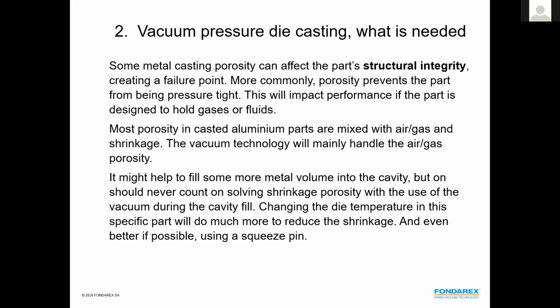The question is always, do you find it out? Does it show up after machining? Are the parts pressure tight, or do they need to be pressure tight? Often the skin on the outside, as long as it's not machined, is good enough that even some little porosity remaining inside the part is still accepted. The shrinkage porosity, of course, is mostly mixed with gas and air porosity, and somehow we have to find a good mix between vacuum, temperature, and sometimes even a squeeze pin, which will do a fantastic job together with the vacuum to create a good pressure die cast part.